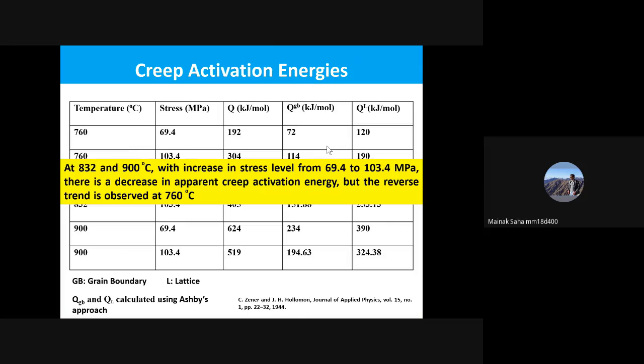At 832 and 900 degrees, with the increase in stress level from 69.4 to 103.4 MPa, there is a decrease in the apparent creep activation energy, but the reverse trend is observed at 760. In other words, when I increase the stress level from 69.4 to 103.4 at 760 degrees, we find that the activation energy, instead of decreasing as it does at 832 and 900, is increasing. This observation is very, very interesting. Of course, this requires extensive microstructure analysis, which is beyond the scope of today's discussion. But definitely, this kind of work is going on.